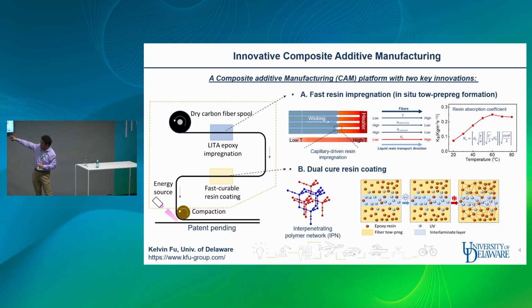So the second part, the second innovation, is the dual cure resin coating. So we developed a dual cure resin. This resin contains epoxy and UV polymers, so they can form an interpenetrating polymer network. This interpenetrating polymer network can help to address the interfacial cross-linking problems. And also they could cure by the UV light to retain the 3D geometry.